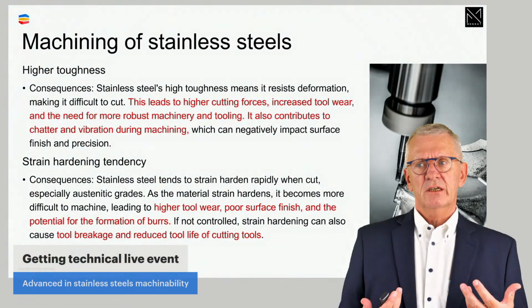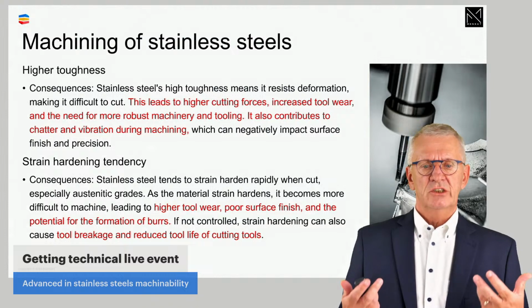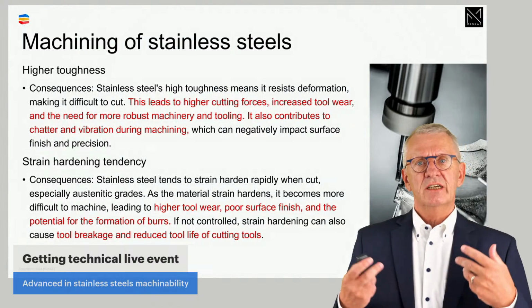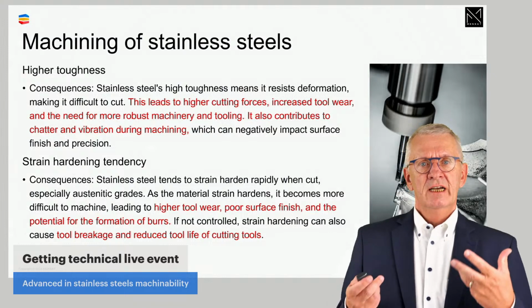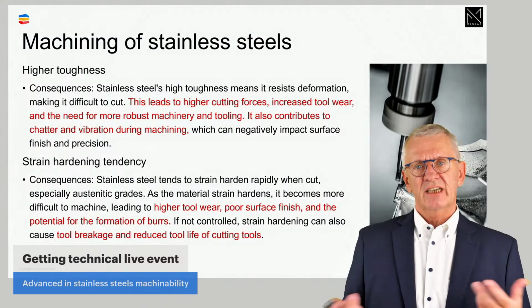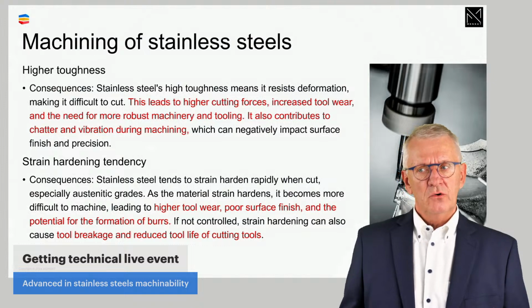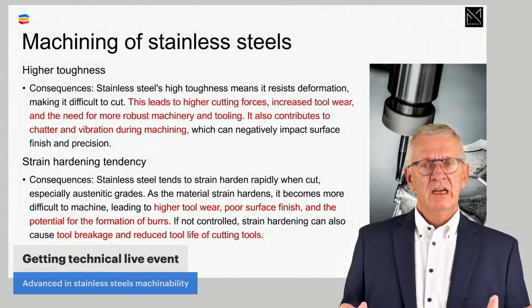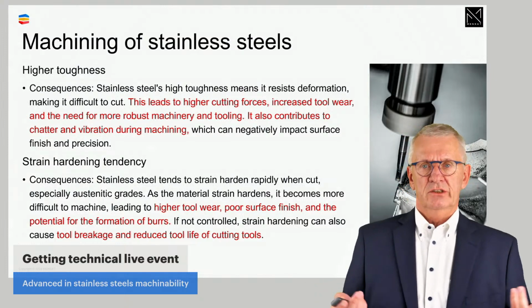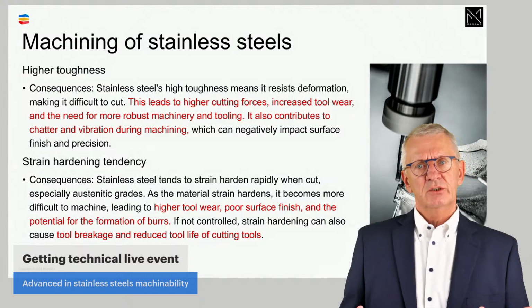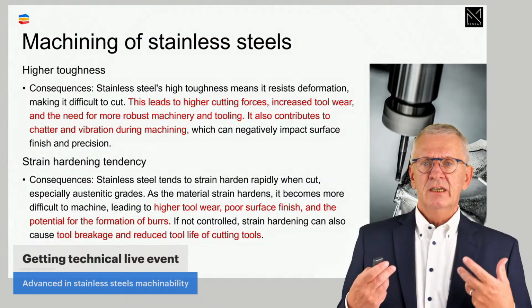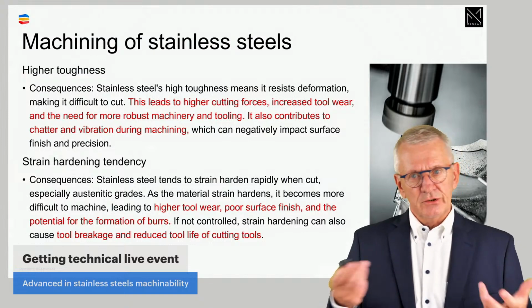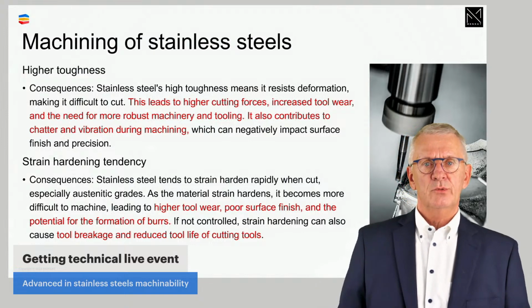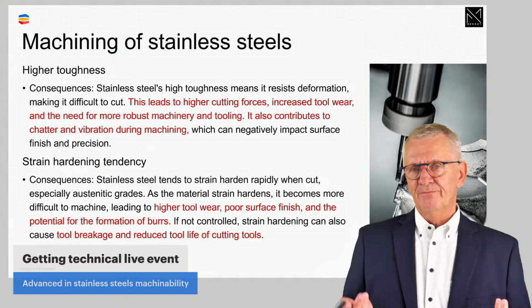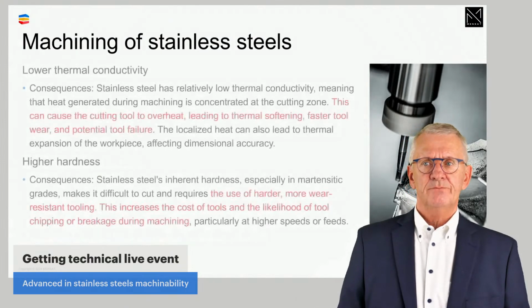We are confronted with a material with a higher toughness. Higher toughness means higher cutting forces. It means increased, faster tool wear. Those are the things we have to worry about. Strain hardening tendency: I have been talking about strain hardening tendency, which is always present to some extent, in austenitic stainless steels, for instance, very much. It leads to very specific tool wear patterns. It leads to surface roughness considerations that are important. Tool life could be limited due to that.